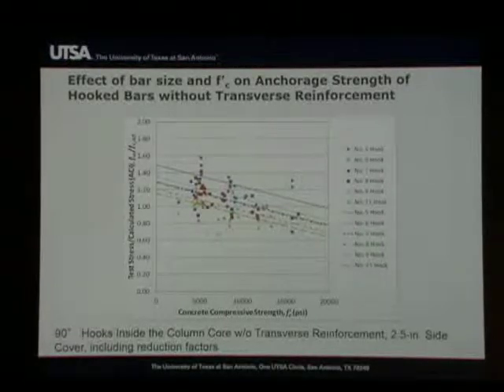What is of greatest concern is if you look at the line right there at 1, every number or line below 1 is an unconservative result. So you see that, for example, the trend lines for number 11 and number 9 bars start to get into unconservative territory at compressive strengths as low as 6,000 psi. If you get up to 15,000 psi, you're looking at measured to calculated values on the order of 80%, which is significantly unconservative. So not only do we have a mismatch on the effective bar size, we certainly have a problem with the effective compressive strength. An objective equation will show trend lines that are flat, not a slope like these ones have.